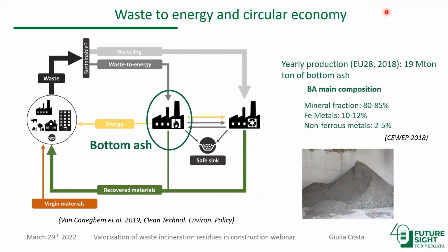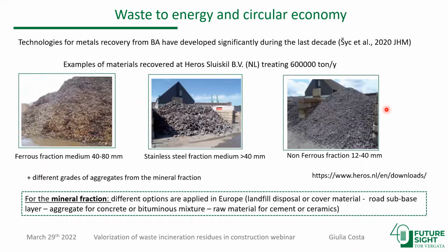Around 20 million tons are produced yearly in Europe, and it presents a ferrous metal content of around 10% and lower content, but still significant, of aluminum and other metals that can be recovered. But the main fraction, the mineral fraction, is being recovered also. Here I'm reporting some pictures from a large-scale plant in the Netherlands, but recently also in northern Italy, several large-scale bottom ash treatment plants have started to operate to recover metals, but also the mineral fraction.